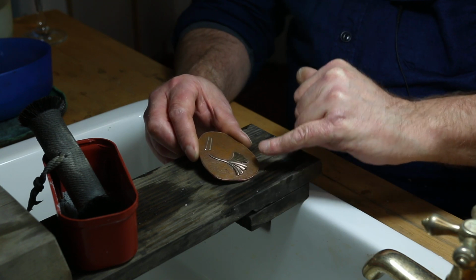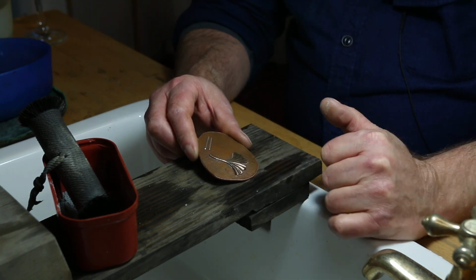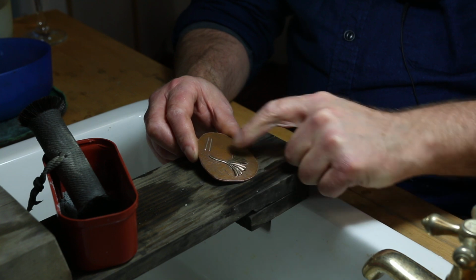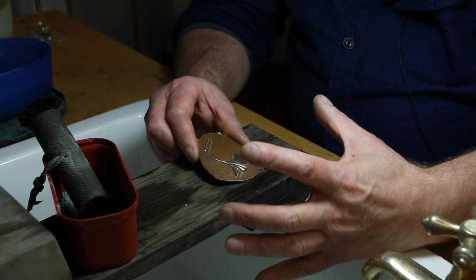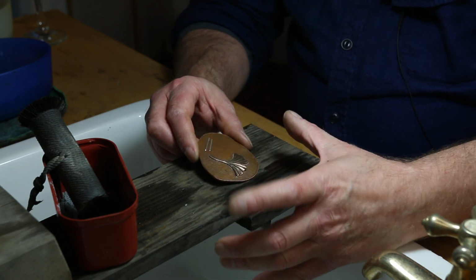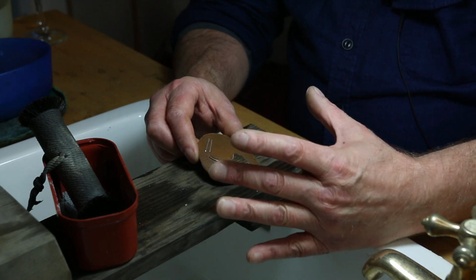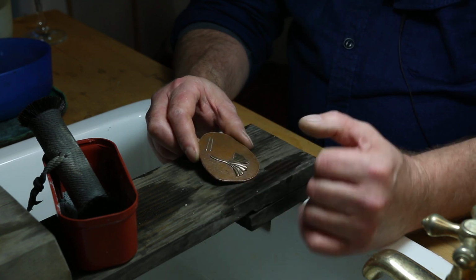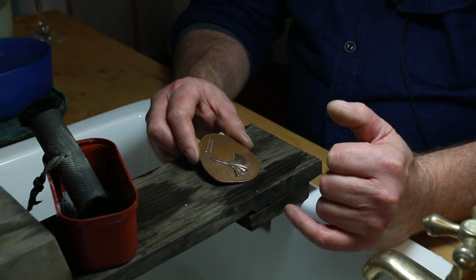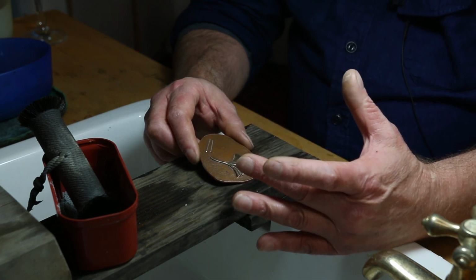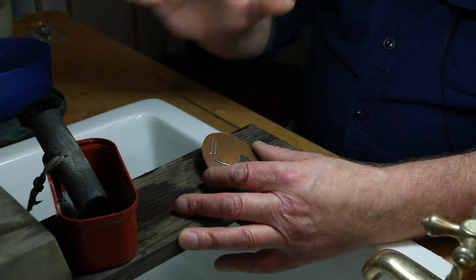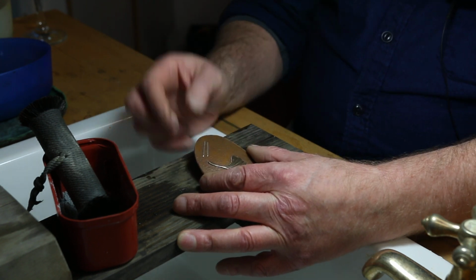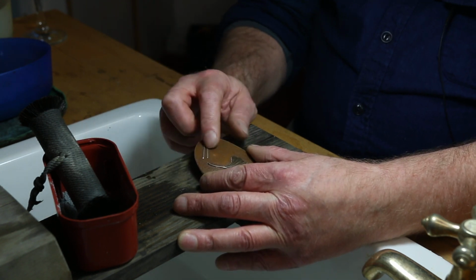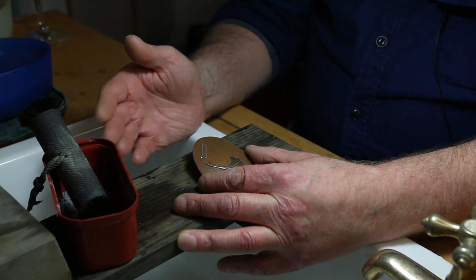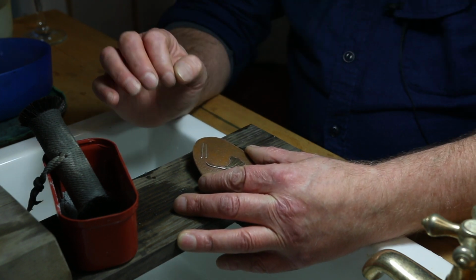What that means is, once that happens, the patina is not going to develop any further. So your copper patina will be stuck in a slightly orangey patina with a slightly yellowy, greeny overtone perhaps. Your shibuichi may have a slightly greenish, yellowish tinge. Shakudo won't have the full black, and your silver, as I say, will have a yellowish tinge. And even your gold inlays will have a slight film on them.